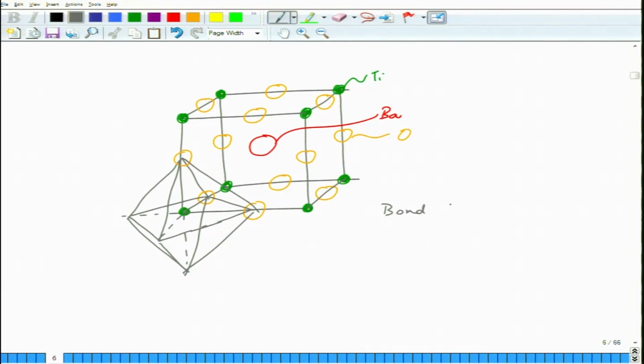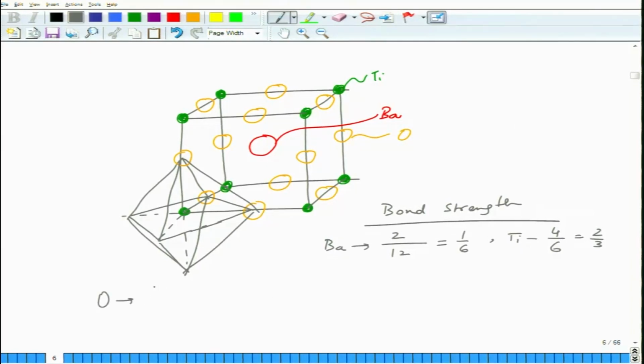You can also do the bond strength check here. Now cation for barium, barium has a valence of 2, it is surrounded by 12, right. Its bond strength is 1 by 6. Titanium has a valence of 4, surrounded by 6. Now oxygen has a valence of 2, coordination number unknown. Either you know the coordination number, or you need to get the valence out. So what you can do is that oxygen valence in this case is